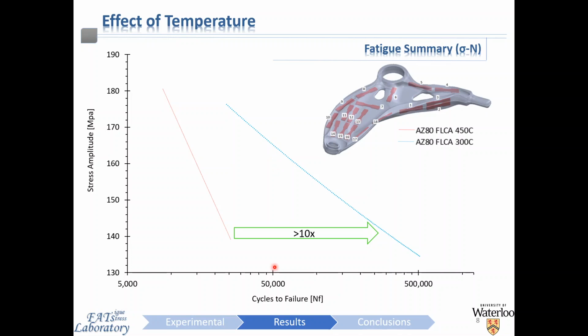Important to note is that the materials being compared are from a full-scale forged component, so the effect of the processing temperature is really the most important in the last step of the thermal history prior to the in-service use. So, i.e., this isn't the extrusion temperature of the material prior to forging, but it is the die forging temperature and the subsequent cooling schedule after forging that governs the final microstructure. Although we did look at a post-forging heat treatment in this particular project, I've chosen not to discuss them here as they're very alloy and application specific.